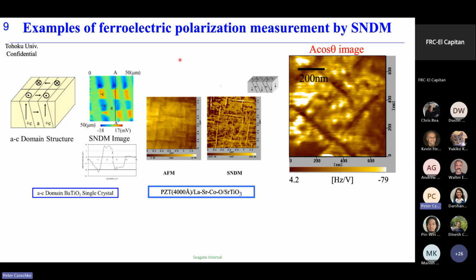And this is an example of the polarization measurement result by SNDM. This is the raw data. The scanning area is very large. This material is the very famous ferroelectric barium titanate. And this is a two-dimensional image. You can see positive C and negative C domains. C means the polarization is in the perpendicular direction. And this is an A domain. An A domain means it has a lateral polarization. Anyway, this one-dimensional profile was taken along this A prime line. If the tip is on the positive C domain with upward polarization, a negative SNDM signal was obtained.